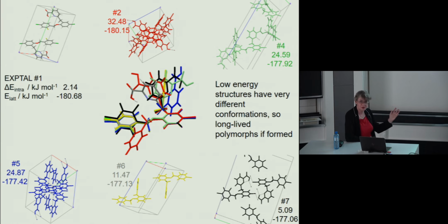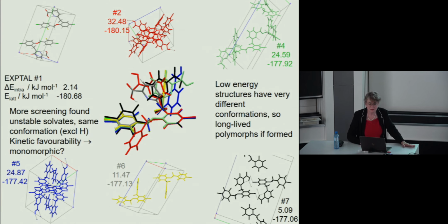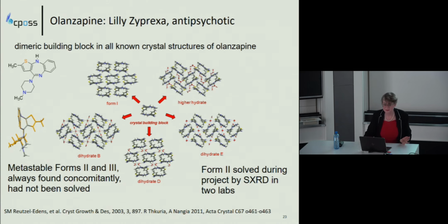So they did go away and do a lot more screening work, and they were able to find some metastable solvates, which did have the differences in the hydrogen bonding, but the rest of the conformation was the same as in the neat polymorph. So in this case, it looked as if the kinetic favorability that the most stable structure crystallized so easily was what was preventing finding any other polymorphs.